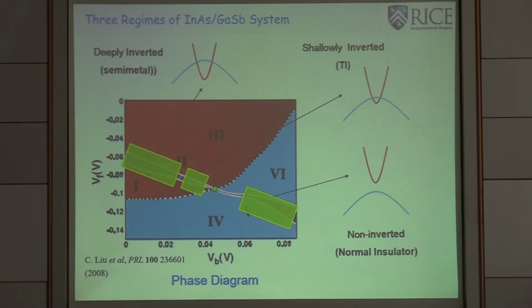But if we take into account the interaction, this critical point or the region around the critical point is actually very interesting because the attraction between the electron and hole will lower the total energy, therefore forming a stable or spontaneous exciton state. Under a very strict condition, it becomes an exciton condensate or exciton insulator. So for today's talk, we basically want to talk about low density, but not as low as getting into the exciton insulator region.